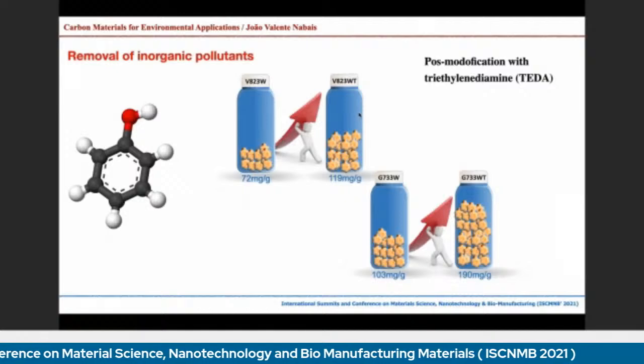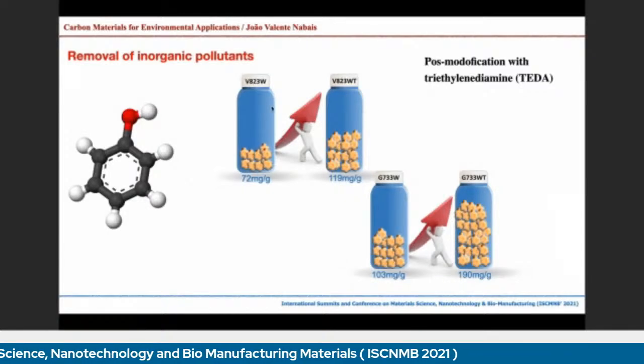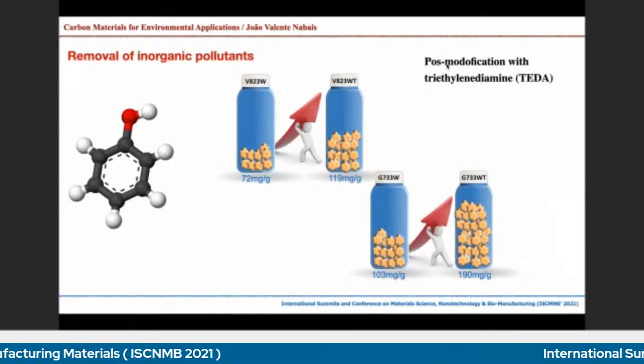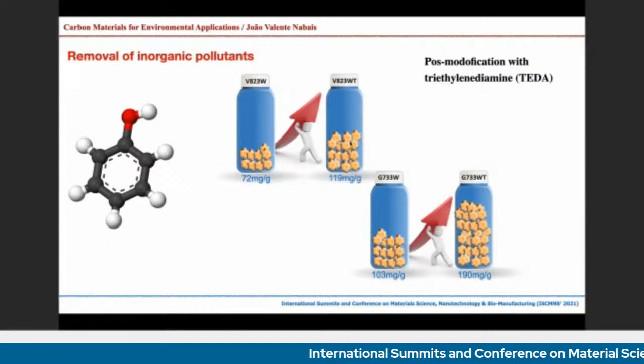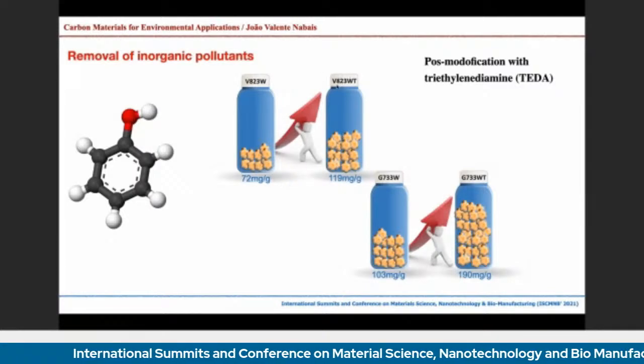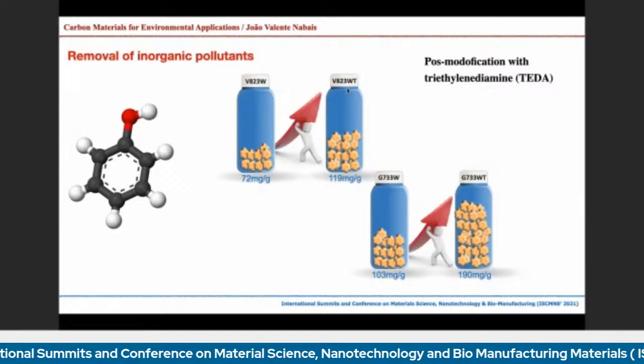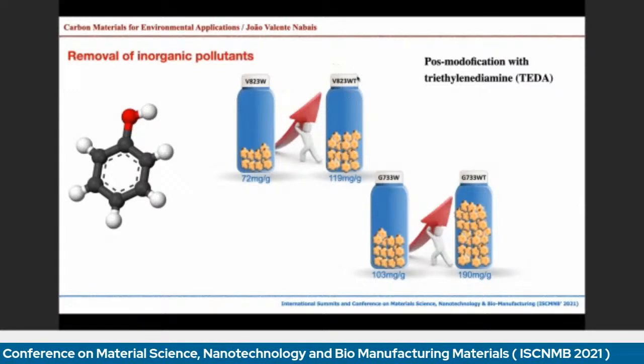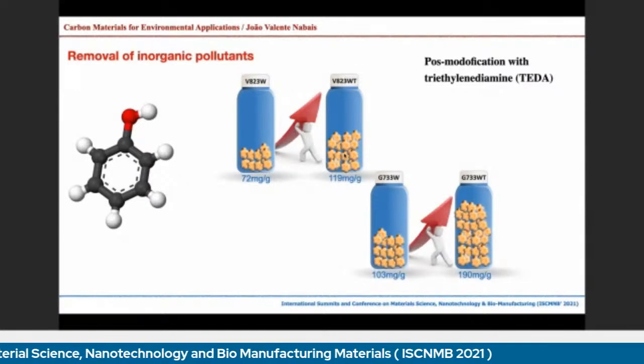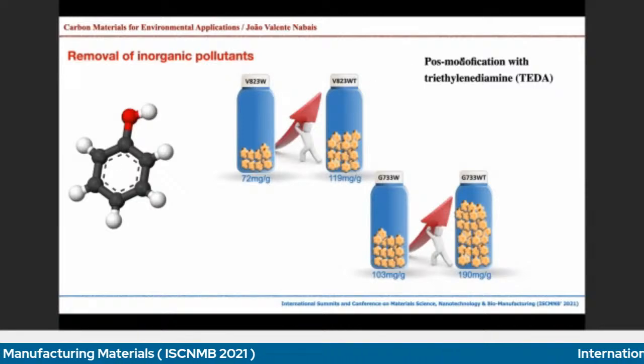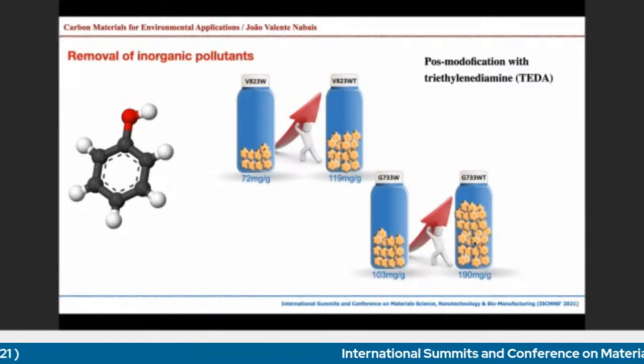More interestingly, if we compare the materials before and after the post-modification with TEDA, you can see that the absorption of phenol almost doubles when we use the carbon materials with modification. So if you want to promote the absorption of phenol, you can use this post-modification to increase it. Why?